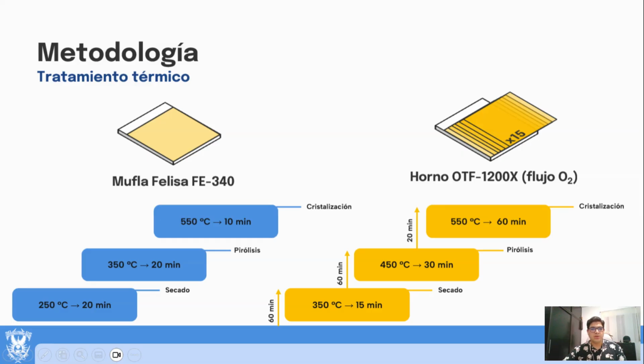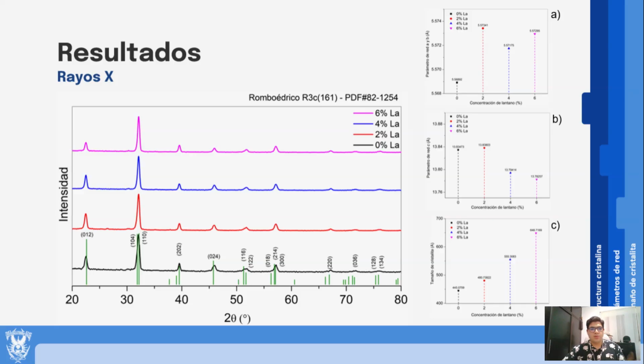impurity formation. X-ray diffraction analysis of doped BFO samples was performed using a Rigaku Ultima 4 diffractometer. The results revealed a pure rhombohedral phase, space group R3C, without secondary phases or substrate interference, as confirmed by comparison with reference. Rietveld refinement in FullProf and microstructure analysis in MAUD provided reliable structural parameters.